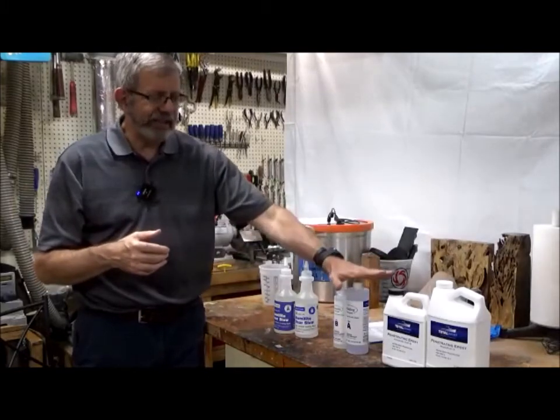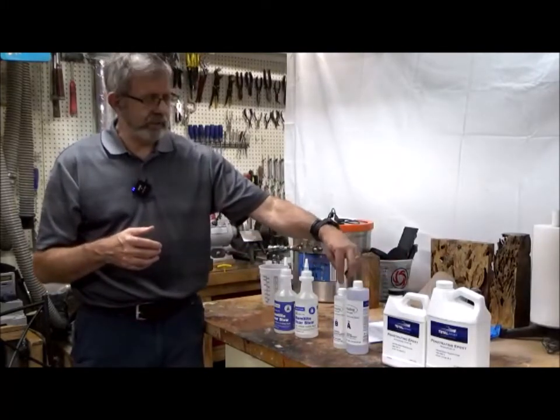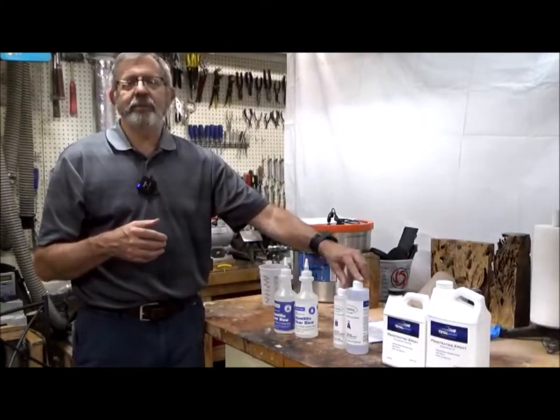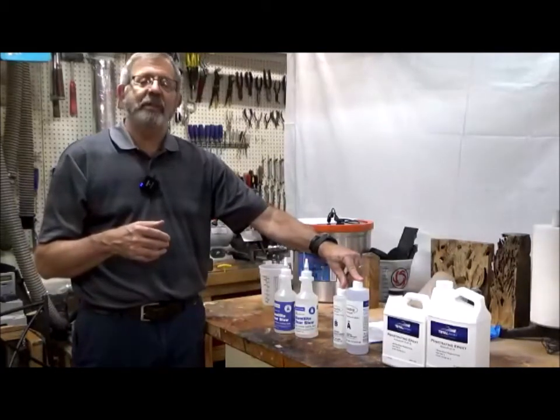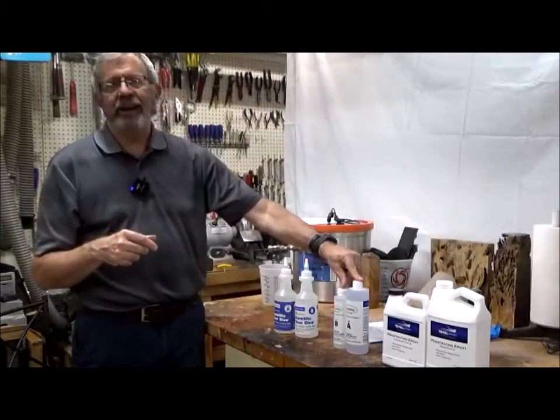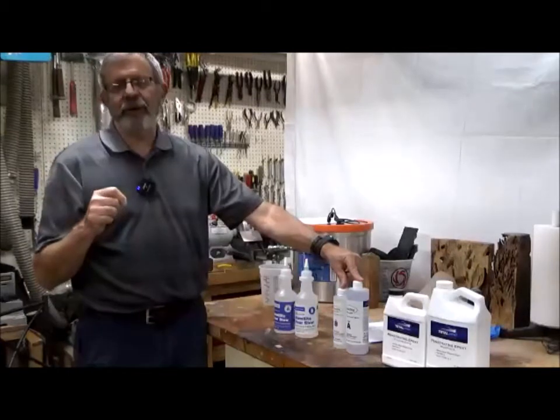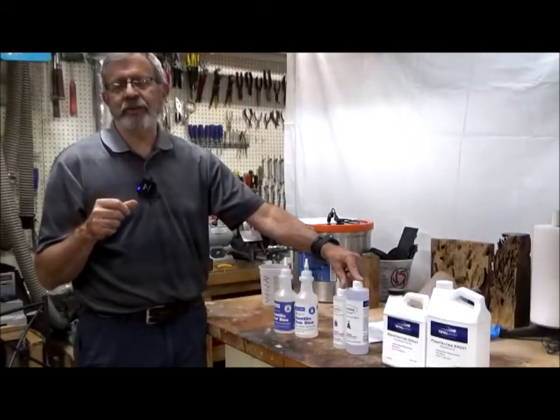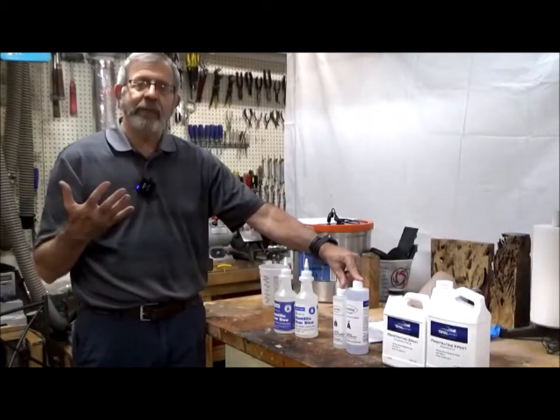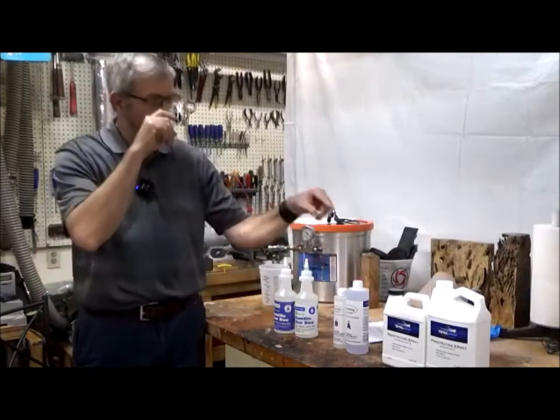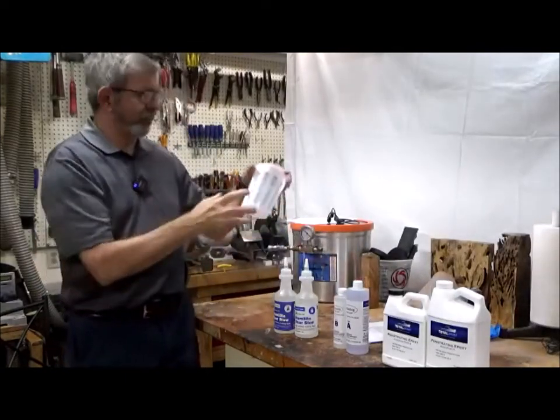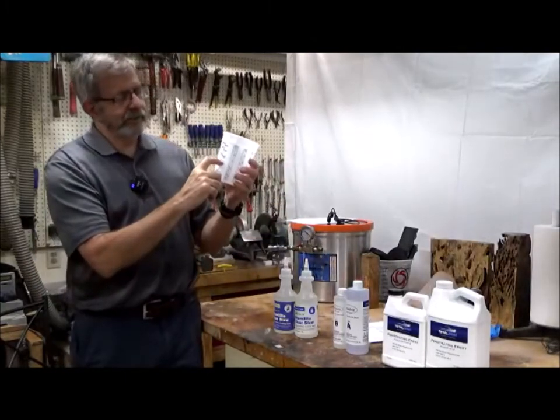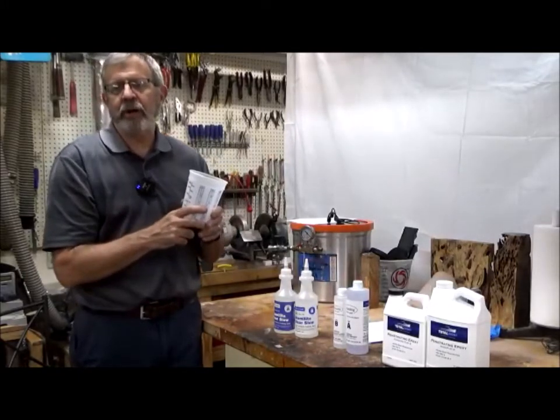The epoxies typically are two parts and one part. Some of them are two to one by volume. Some of them are two to one by weight. I tend to convert everything by weight because it's a lot easier to measure accurately by weight than by volume. If you look at the markings on a mixing cup, you could easily get something wrong on here.